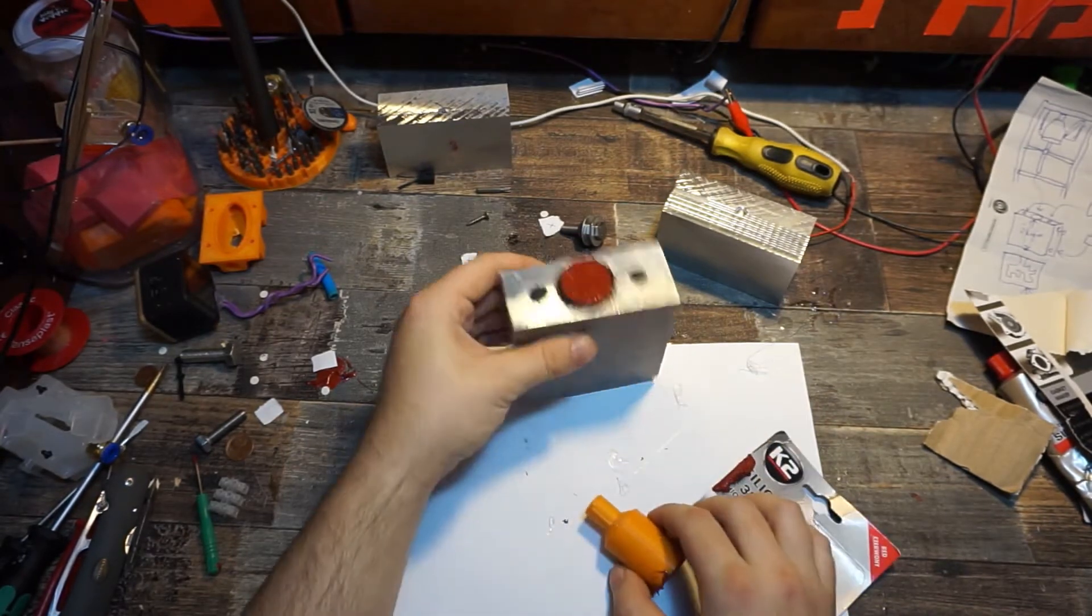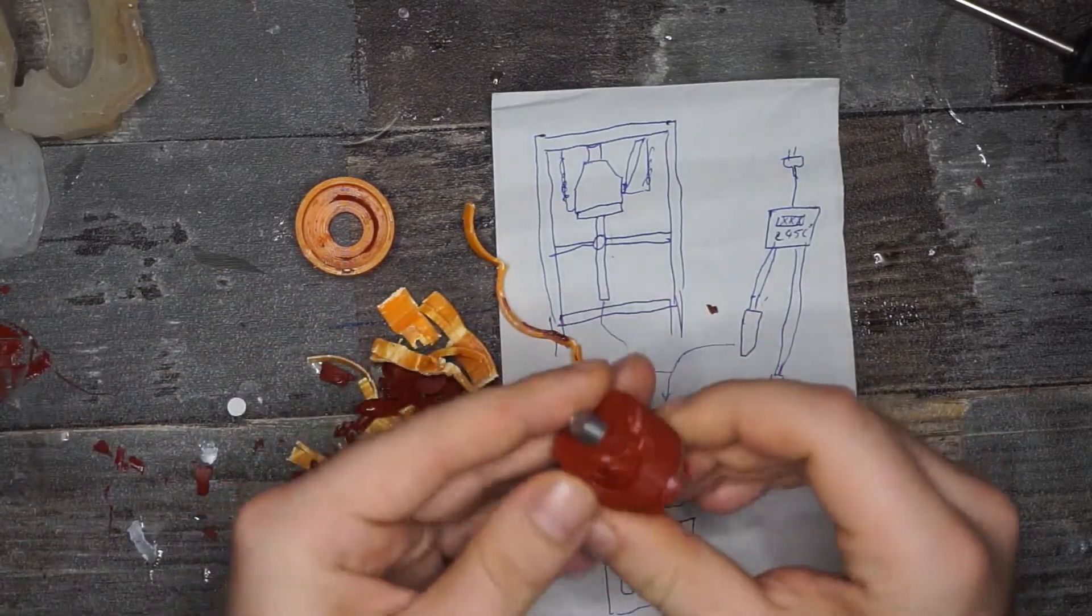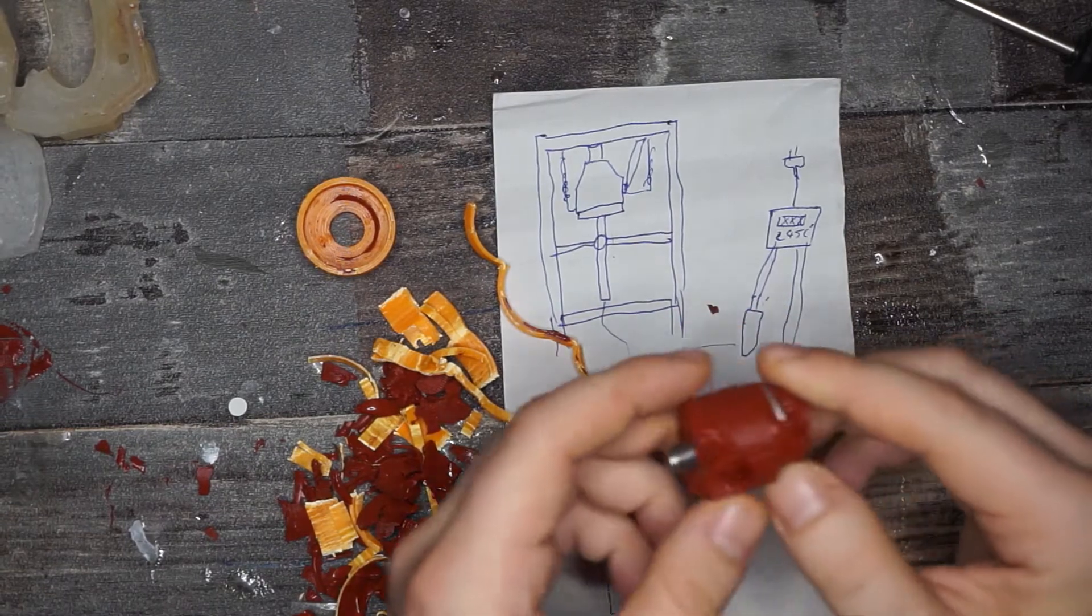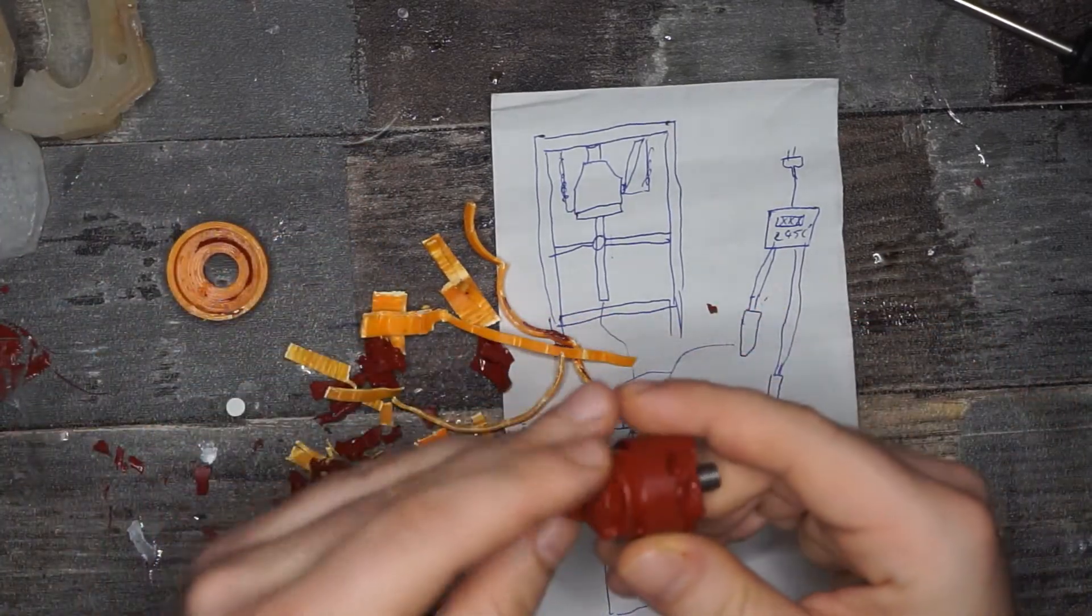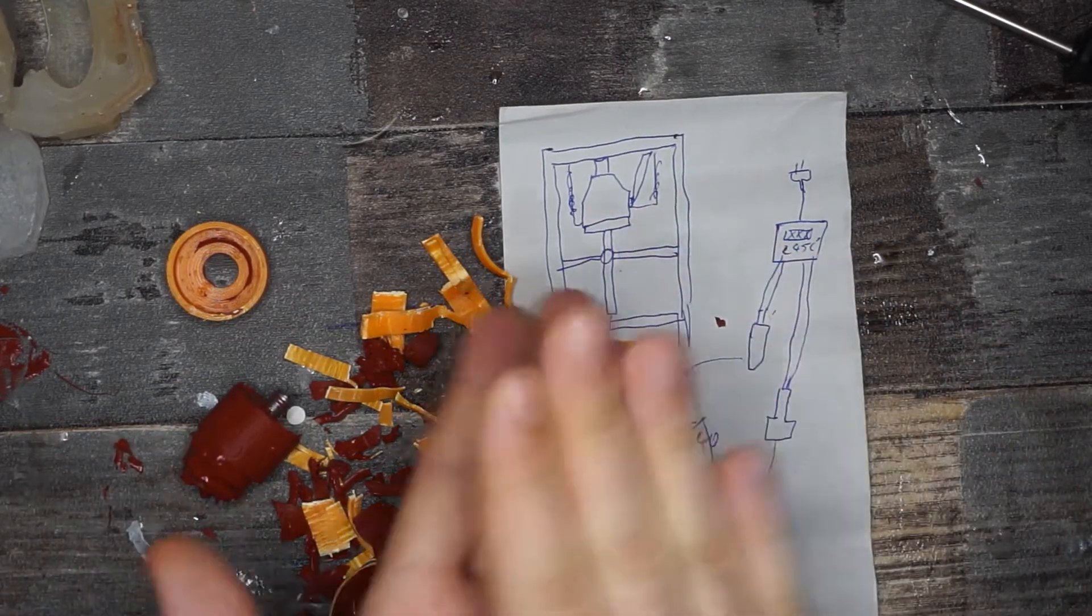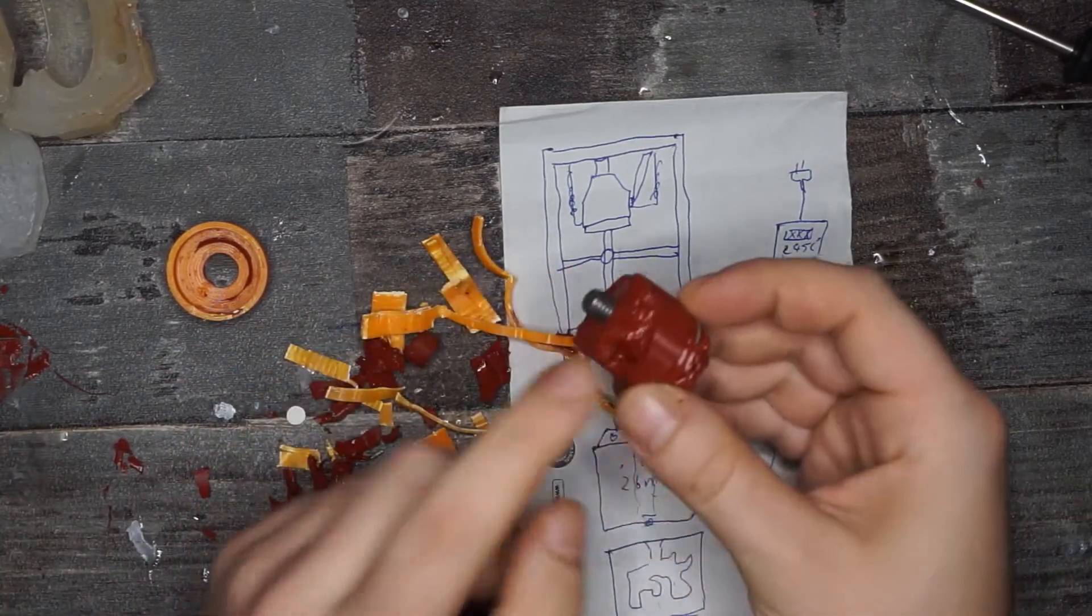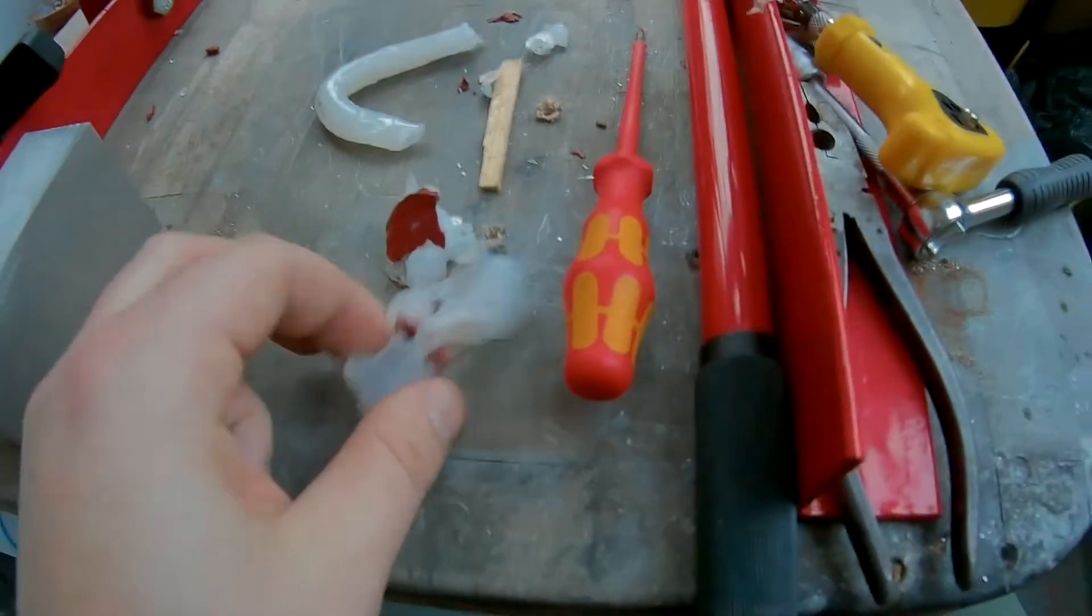Hey, it's me from the future. Just a short thing: I tried this and it didn't work out well. It took almost two weeks to completely dry, and then when I took it out from the cup, a few things ripped off and there are air bubbles inside. No, this thing just didn't work. That's why I used the high temperature silicone to make some baffles and stack them on top to make a sealing. I actually was doing this in the time where this thing was drying.